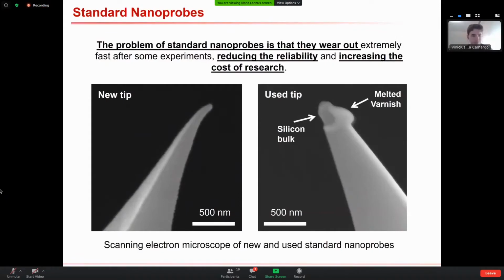Yes. So the radius of the tip of the AFM can be different for different types of tips. It can go from, let's say, 2 nanometers as the smallest, up to 200 nanometers, depending on the coating that you use. You will increase the radius, but if you use thicker coatings, you will increase the stability of the coating. So it's a kind of trade-off. It depends on which material you use. You will get more stability, but less resolution, or the opposite.